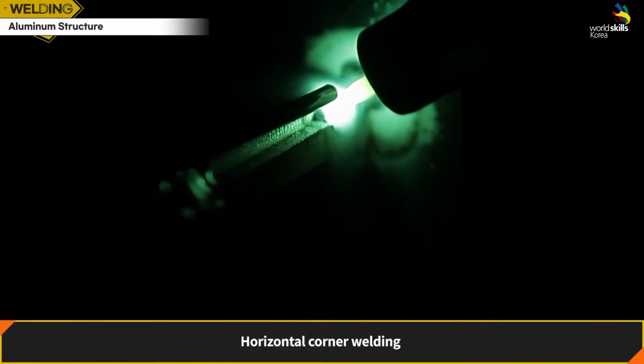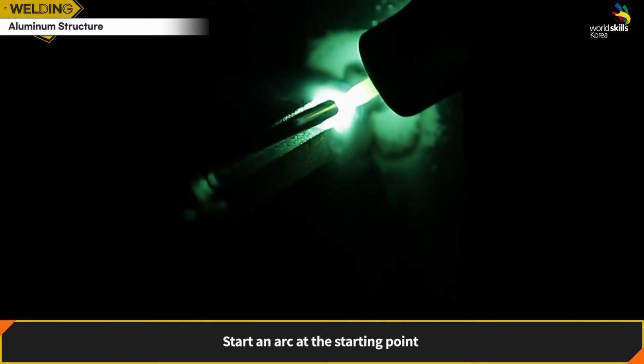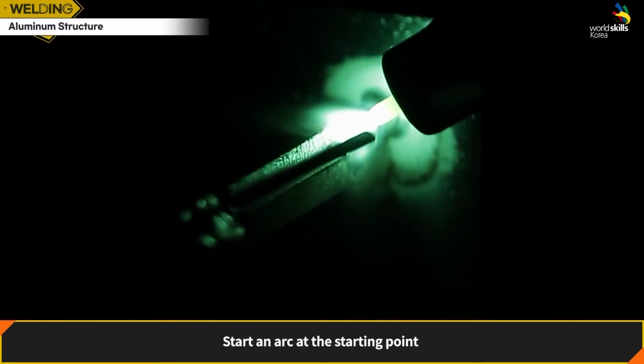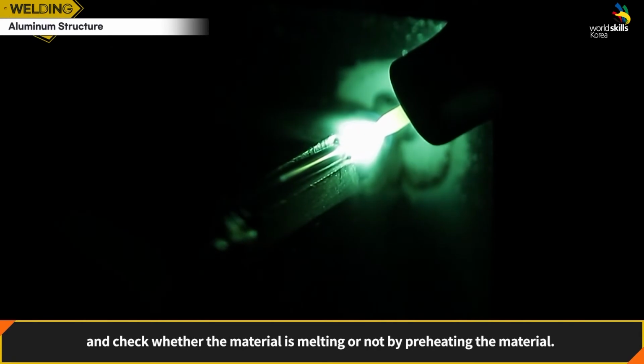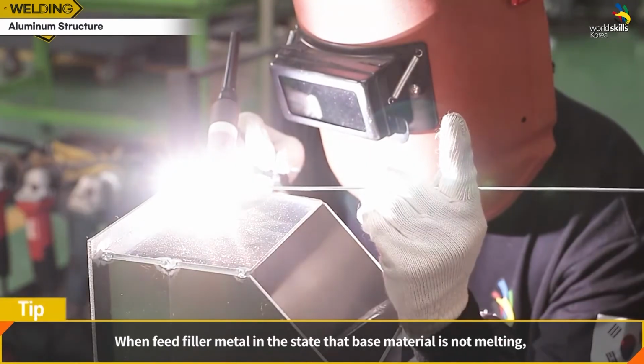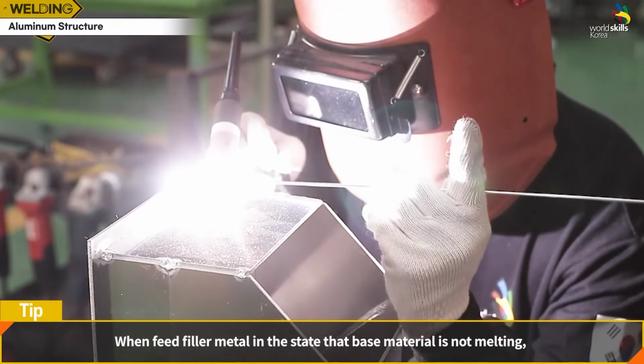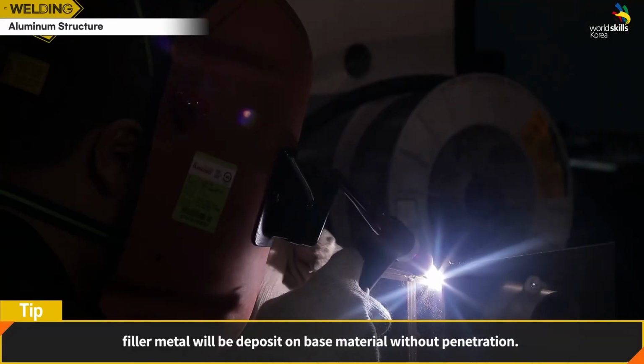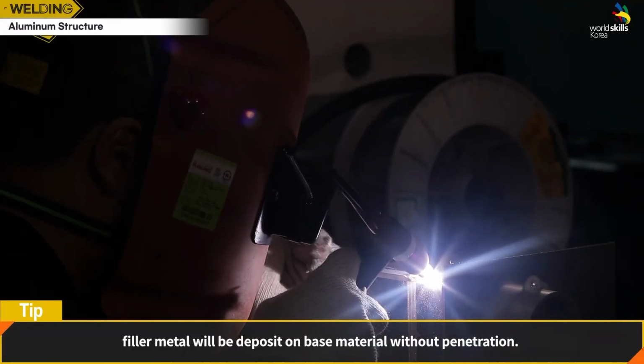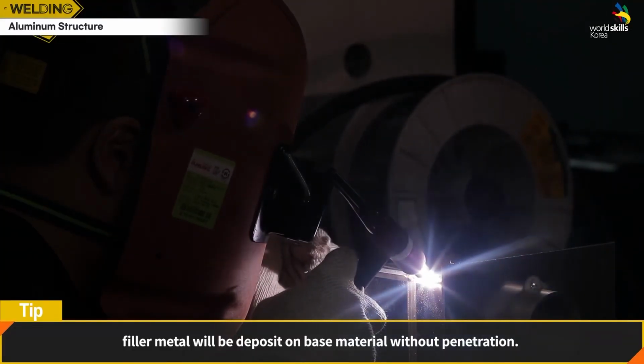Horizontal corner welding. Start an arc at the starting point and check whether the material is melting or not by preheating the material. If the welding rod is placed in the state that the base material is not melted, it will not penetrate and will be rounded up on the base material.